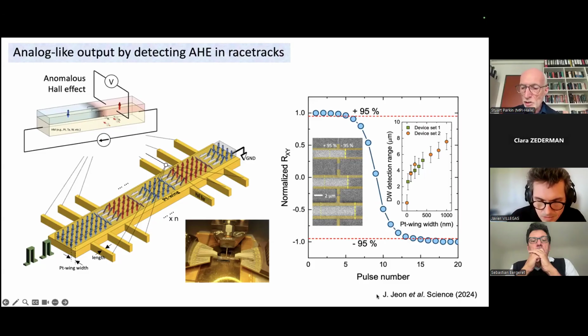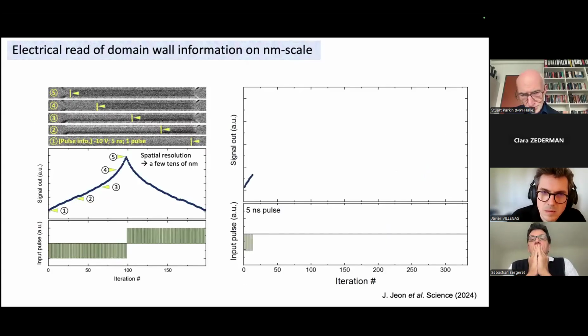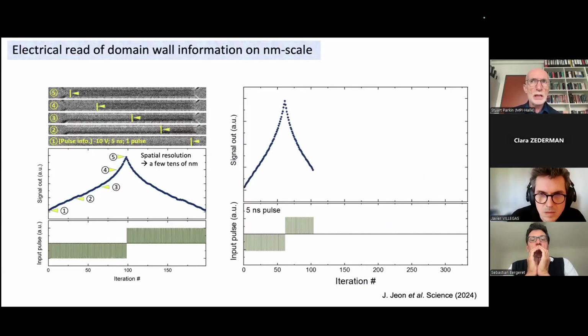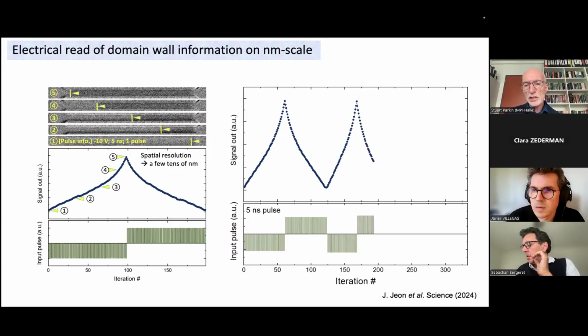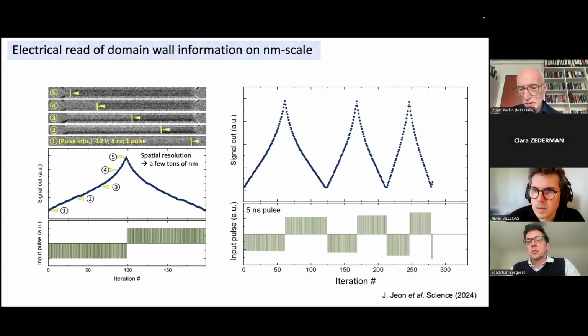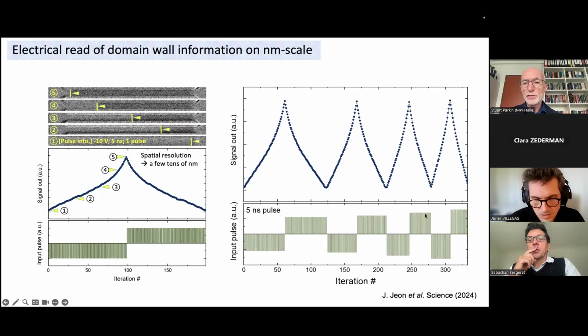And this is a paper we published in Science just last year, demonstrating that we could see the current-induced motion of single domain walls in racetracks that are only 50 nanometers wide. And so here, for example, you can see the signal from these anomalous Hall detectors, which we have built along a single racetrack. And this shows you when we introduce 5 nanosecond long current pulses, each pulse moves the domain wall a little bit, and enough pulses will take the domain wall from one end of the racetrack to the other, and then we switch the sign of the current pulse to move the domain wall backwards.